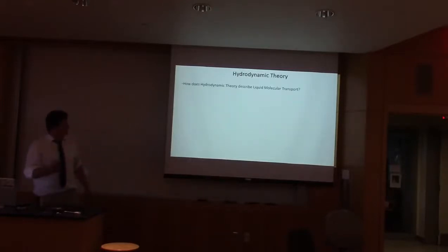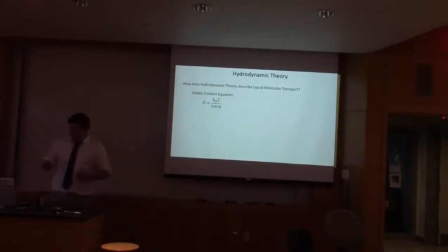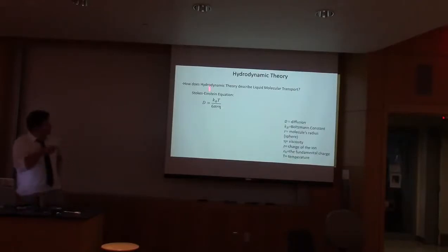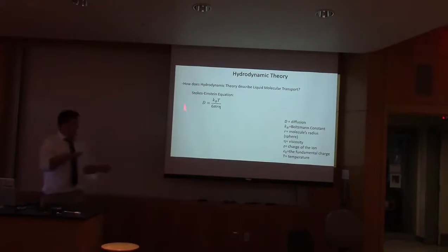Hydrodynamic theory basically describes liquid molecular transport properties as being interrelated. The Stokes-Einstein equation relates diffusion as being equal to the Boltzmann constant times the temperature divided by 6 times pi times the radius of the molecule, assuming it's spherical, times the viscosity. This means that diffusion, a molecular transport property representing mass transfer in the liquid, is actually dependent upon another macroscale property, viscosity.